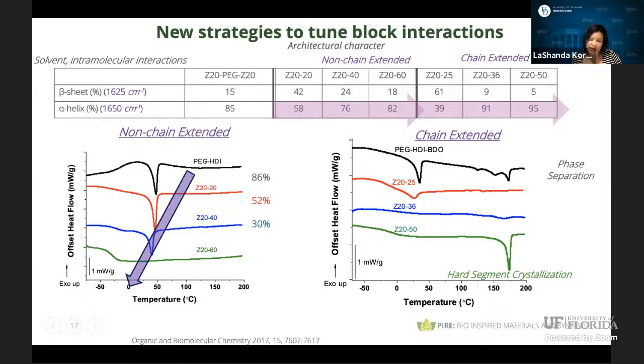So there are a couple of things that come to mind when we start to think about these particular systems. One is we always want to try to understand what's happening with the soft block in terms of secondary structure. So we are using solid state NMR to look at the beta sheet to alpha helical content. For our Z20 PEG Z20, we actually have about 85% alpha helical structures. One thing to note is that when we're making these systems, we actually use DMF, which is a helicogenic solvent, to promote a higher fraction of our alpha helical structures.